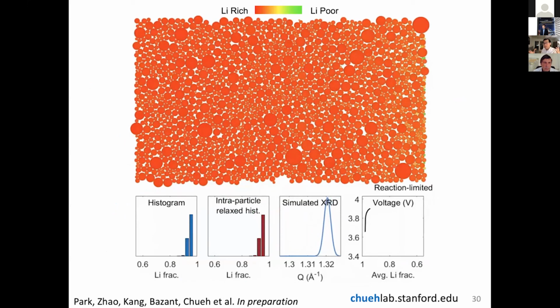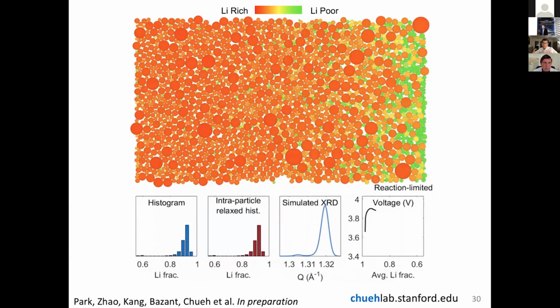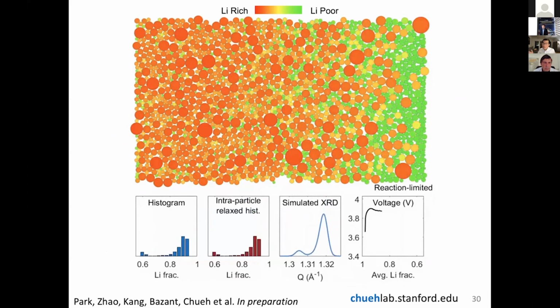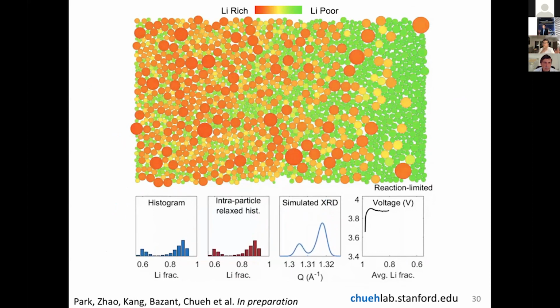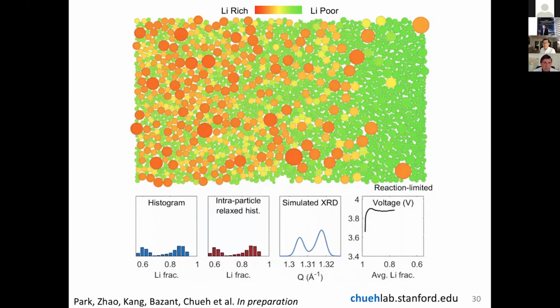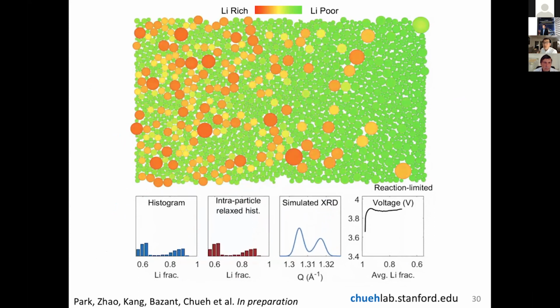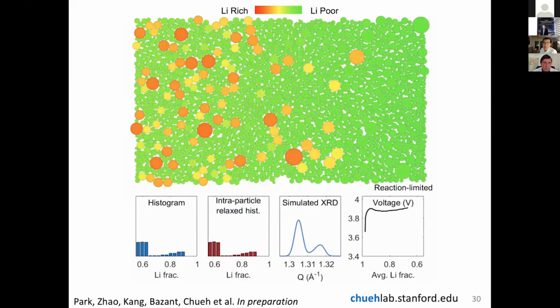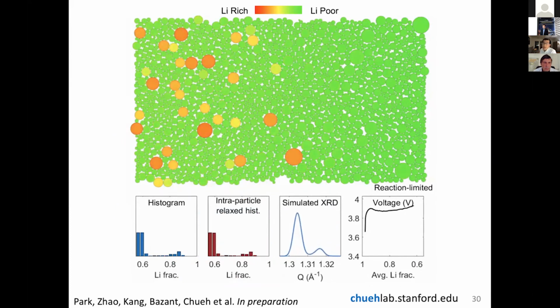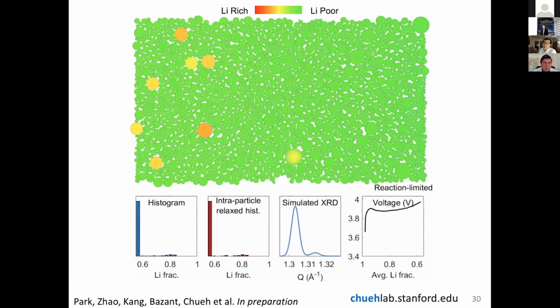And then when you do this at the porous electrode level, so you have a very thick battery, you can still see the same effect. You have the moving front at the electrode level, but you still have this mosaic effect, this heterogeneous effect. So it is not just some random heterogeneity, it is a direct result of autocatalysis.